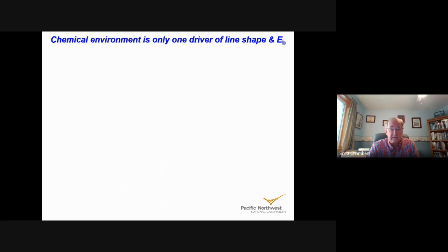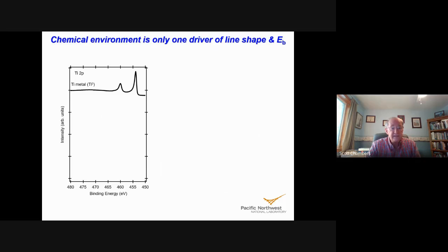And I want to illustrate this and actually drive the point home by looking at some spectra for titanium. So I'm going to show you 4 different materials, and we're going to look at the titanium 2p spectrum. We'll start with a thin polycrystalline clean metal that was grown in the same chamber as the photoemission was done in. And so there's the spectrum. Well, you notice it has 2 peaks, not 1, and that's because of another effect that's very important, and that is spin-orbit coupling. So we'll introduce that now.